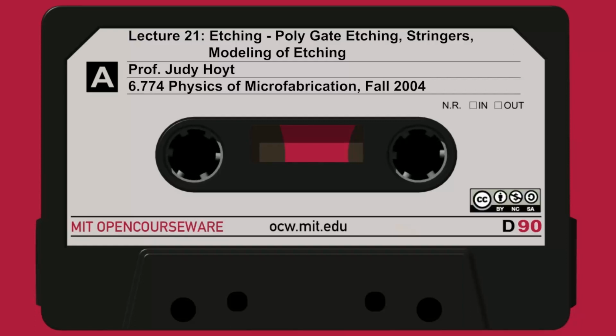If we go on to slide 10, this is just an example of a recipe if we were to use that Lam TCP 9400 gate etcher. I took this off the Stanford website. This is an actual recipe that they have published showing the individual steps that you would need to use, just to give you an idea of some of the complexity of this etch process. Now each step, they're numbered here 1 through 9, corresponds to a different time sequence. A different step in the time sequence for the etch. So the very first step, labeled number 1, you're adjusting the gap, which is a parameter inside the tool. The pressure is being stabilized at 13 millitorr automatically by the computer, and you're setting up to flow some of your initial gases. You're flowing C2F6, and once you've stabilized after 20 seconds, you go on to the next step.